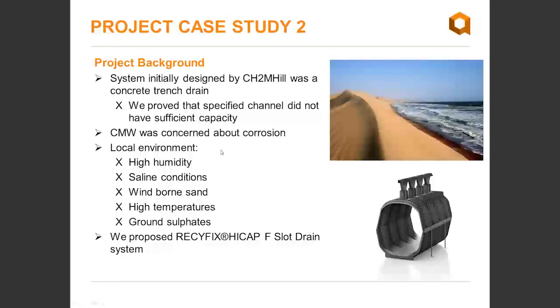Now initially CH2M Hill specified a concrete trench drain system for the area, and through our hydraulic design system, we proved that the specified channel didn't have sufficient capacity. Another concern for the client was the environment, because the environment in the Middle East is very corrosive. You have a mixture of high humidity, saline conditions, windborne sand that sandblasts materials, high temperatures, ground sulfates. That cocktail is very aggressive. So we proposed the RECYFIX HICAP F slot drain system, which is a high capacity slot drain system.